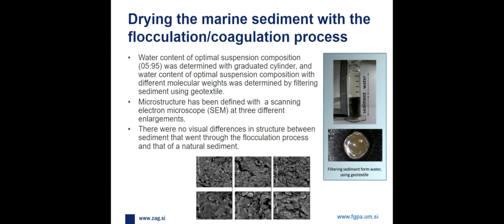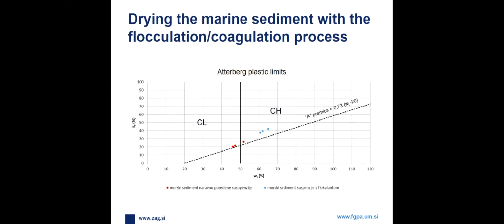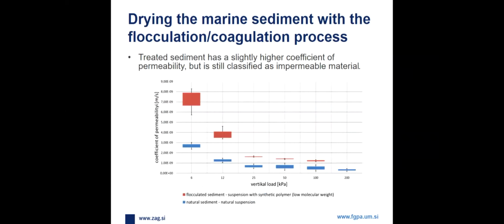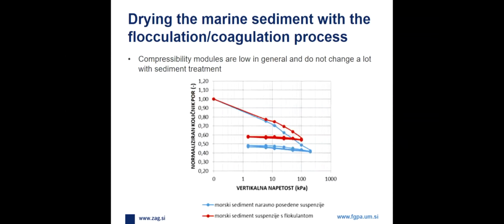This can be proved by the other tests. So yeah, Atterberg plastic limits did not change very much. Slightly, but in general, we still deal with the same material. Water permeability, we can see at very small load, is significantly higher, but as soon as you load this material, the structure collapses and permeability becomes the same as in the natural material. And unfortunately, stiffness also did not change. We would prefer if it would, but unfortunately this is not really a treatment which would be helpful for further use of these materials.